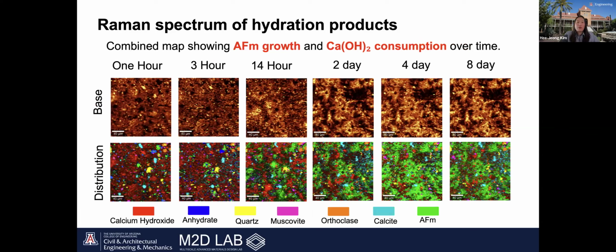And in the modified R3 test, calcium hydroxide was mixed with the supplementary cementitious materials and cured at 50 Celsius degree for 10 days. And the Raman spectra collected over time were used to observe these changes. On the slide, you can see the raw spectrum and the distribution map taken after an hour. The distribution map shows that the AFm phase keeps growing over time, and this confirms that the main hydration product formed during the reaction is AFm phases.